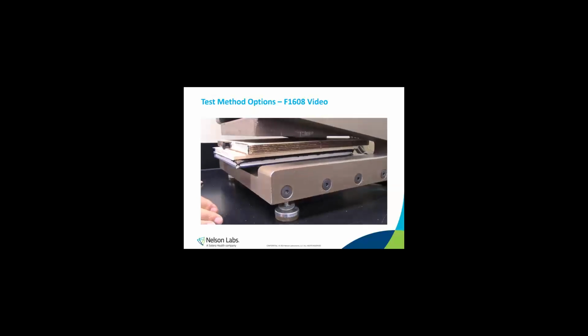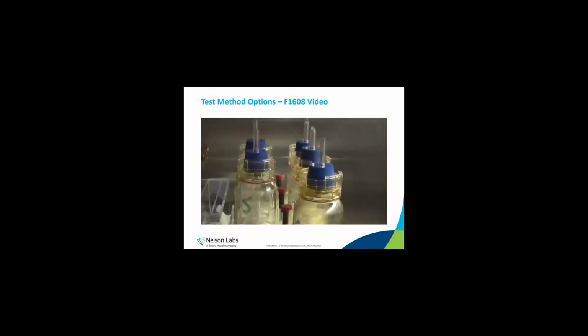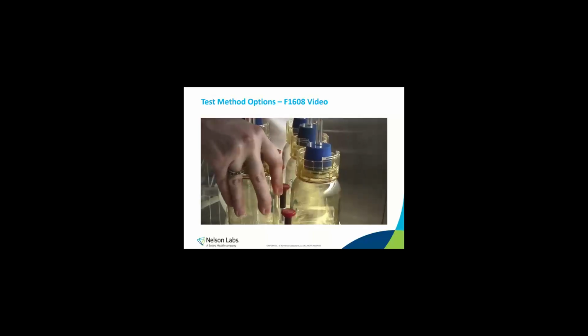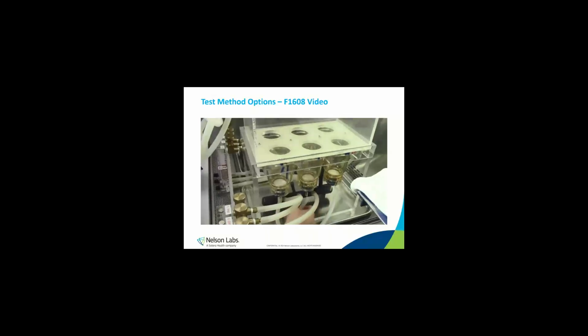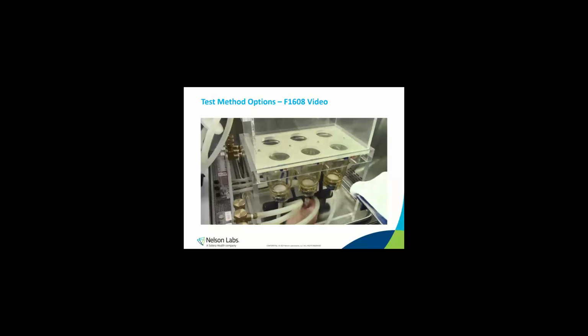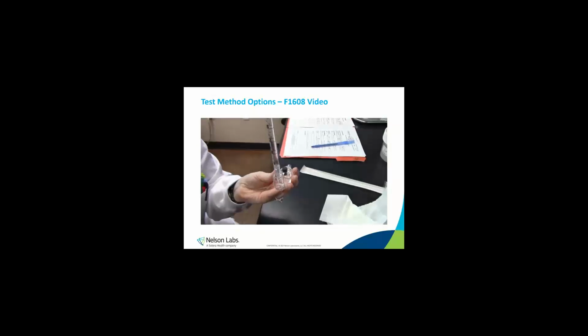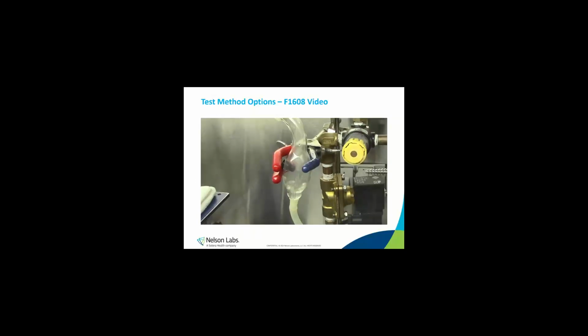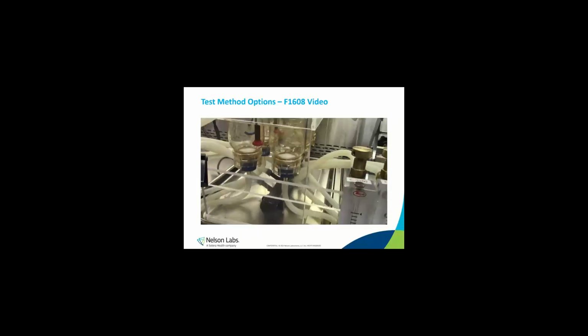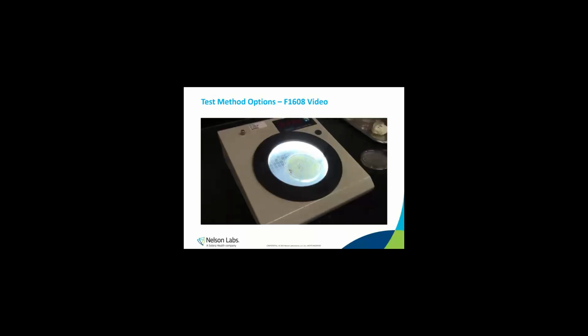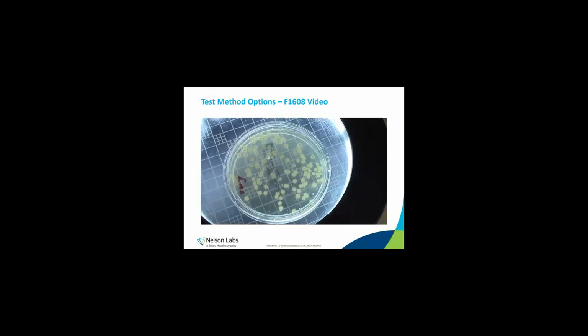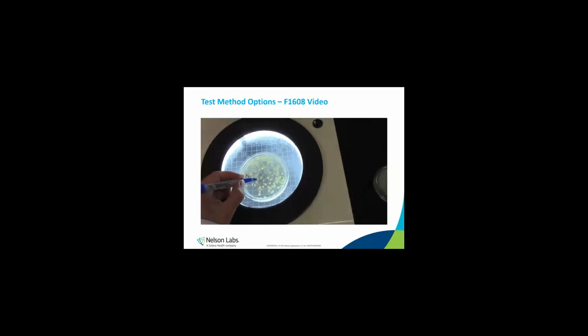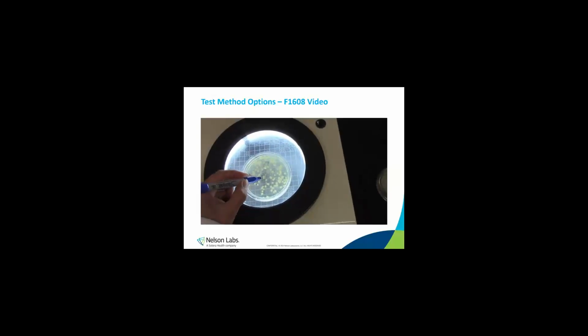We cut a 47 millimeter disc, and then we're going to put it in our test apparatus. We can accommodate up to 5 samples in here, but we're only required to test 2 for the standard. We're going to use a nebulizer to create an aerosol, and then we're going to run this at a set flow through our test system. We'll collect what comes through, we'll enumerate that, and we'll take the log reduction value of the positive versus the samples to give you that log reduction value.